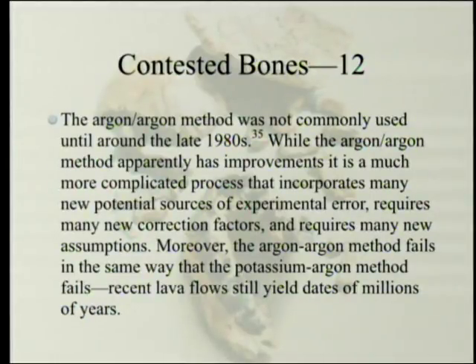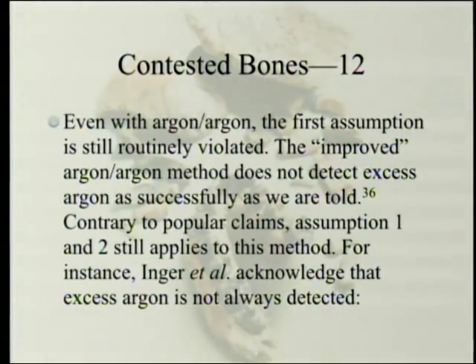While the argon-argon method apparently has improvements, it is a much more complicated process that incorporates many new potential sources of experimental error, requires many new correction factors, and requires many new assumptions. Moreover, the argon-argon method fails in the same way that the potassium-argon method fails. Recent lava flows still yield dates of millions of years. Even with argon-argon, the first assumption is still routinely violated. The improved argon-argon method does not detect excess argon as successfully as we are told. Contrary to popular claims, assumption 1 and 2 still apply to this method.